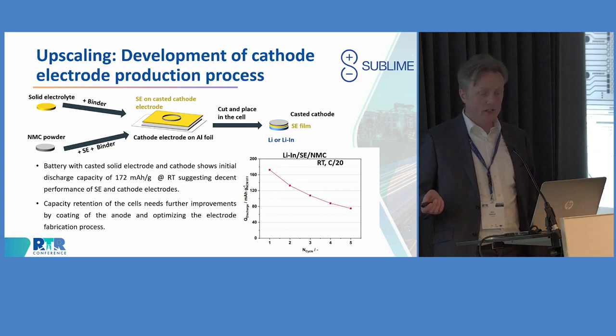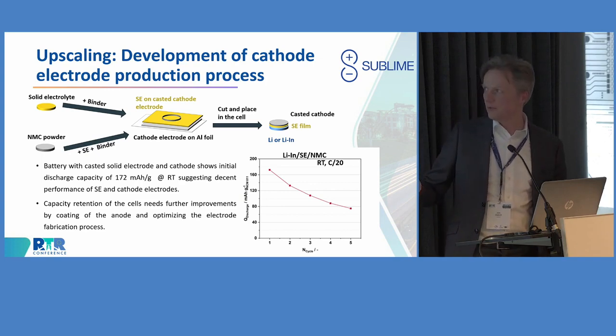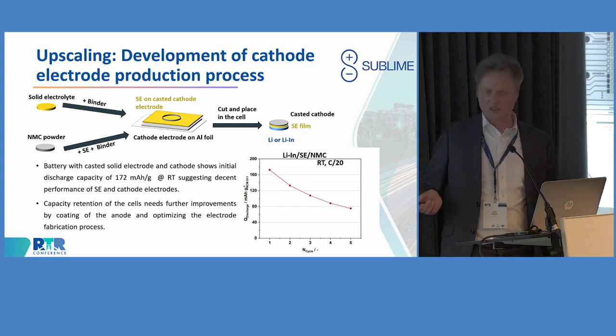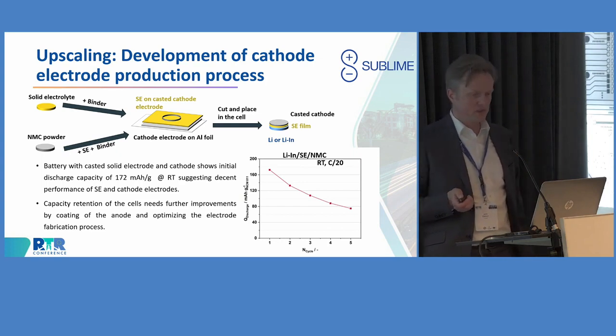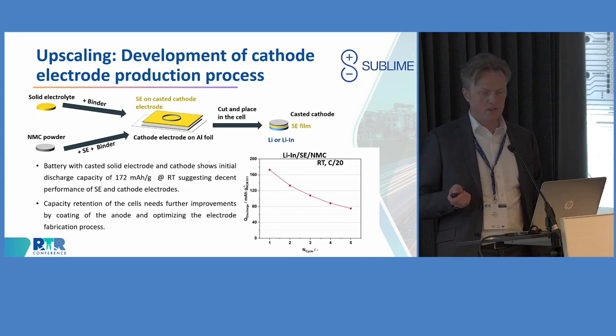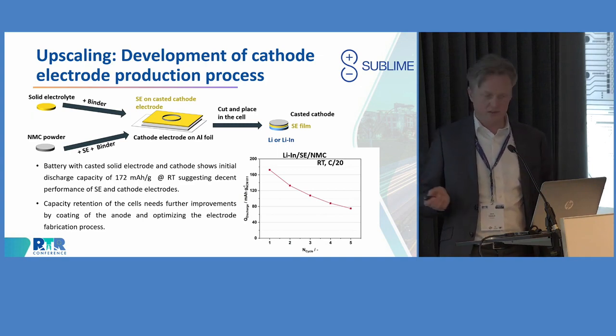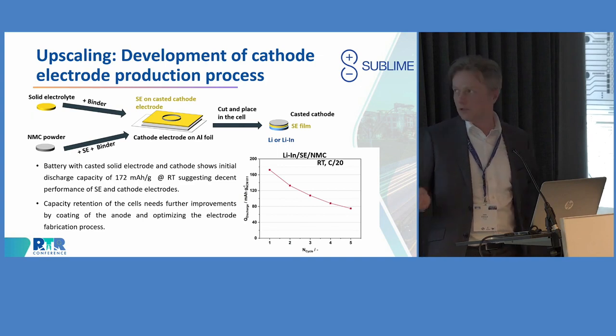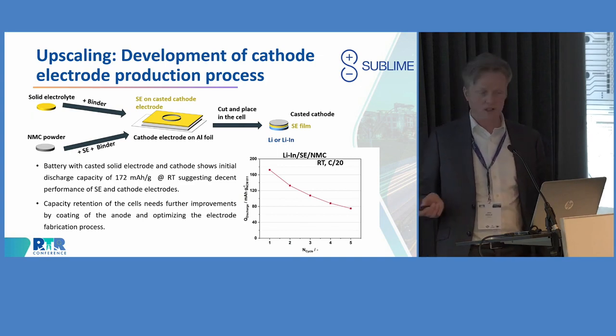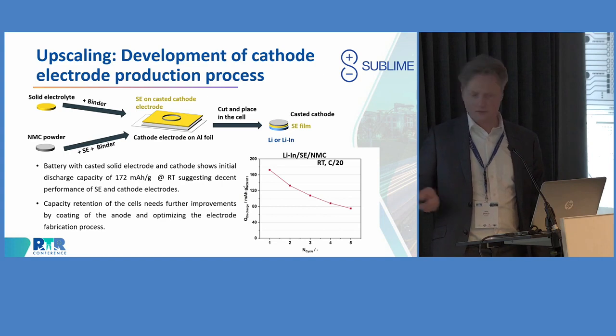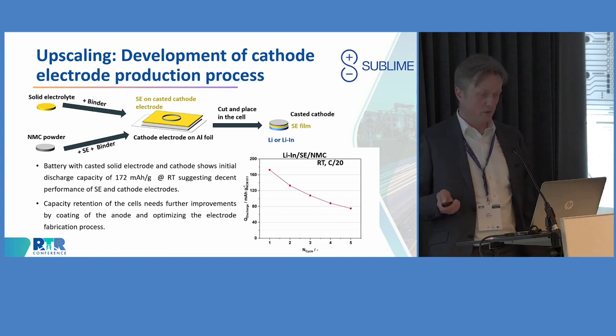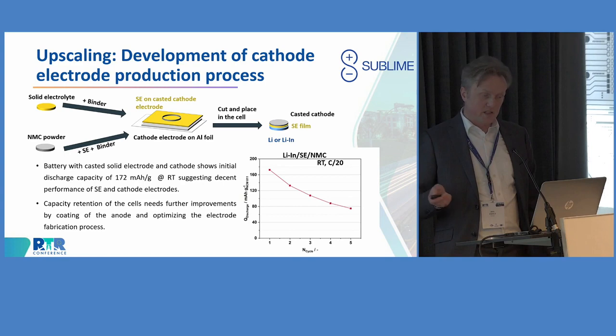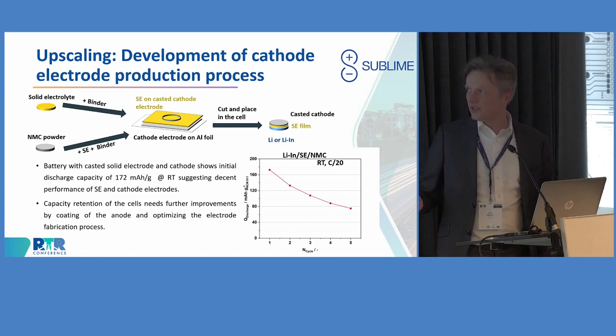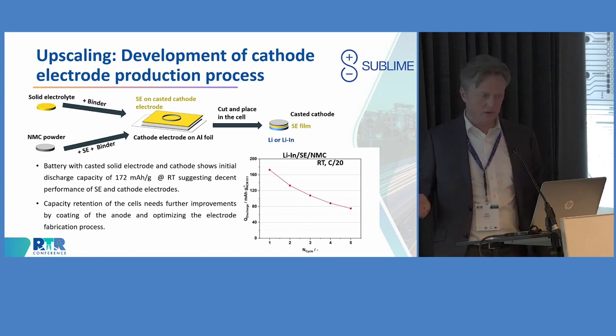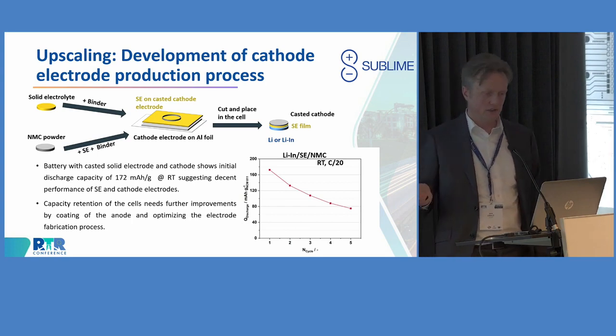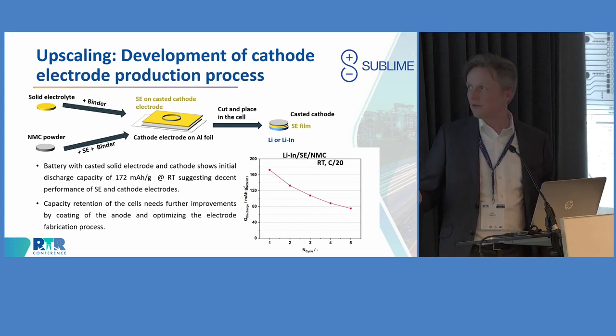So this is working. However, of course, because of the challenges that we see here on the anode side, we are using an intermediate step, exchanging lithium intermediately against lithium indium in order to be able to continue on the optimization here. And once we have done that, then we would come back to the lithium. I will show this. So it needs further improvements, of course, but I think this is the way that we can do, and we still have 1 year ahead of us, so there will be still enough time to do